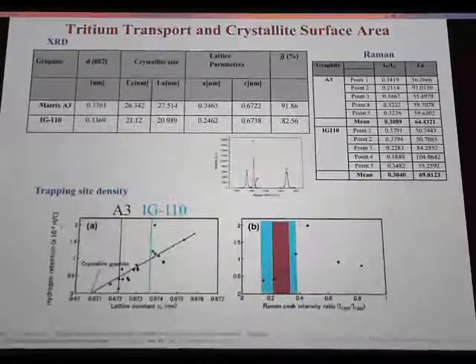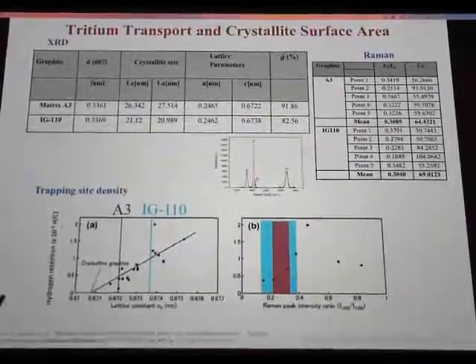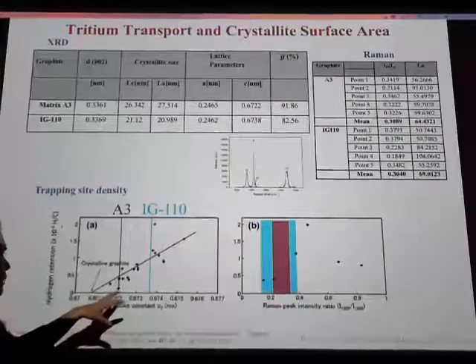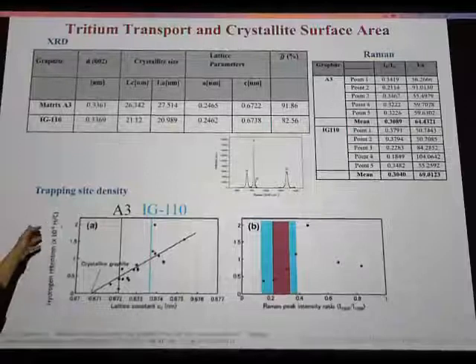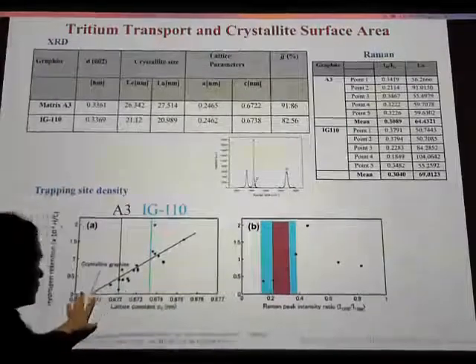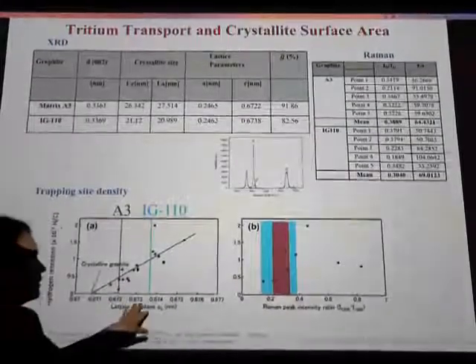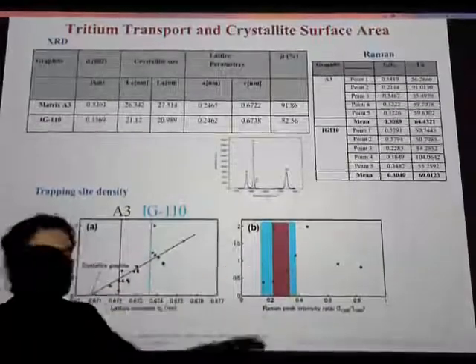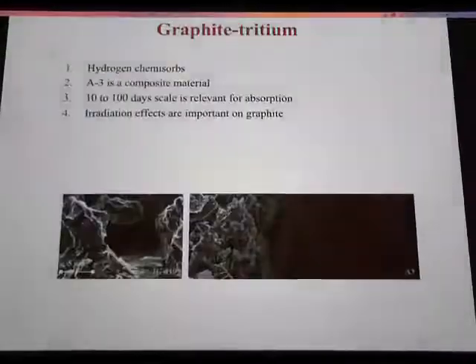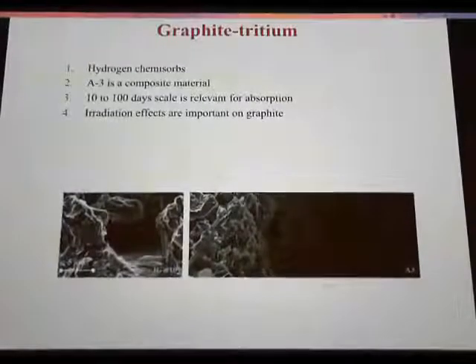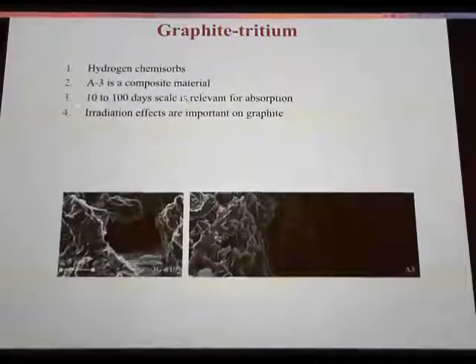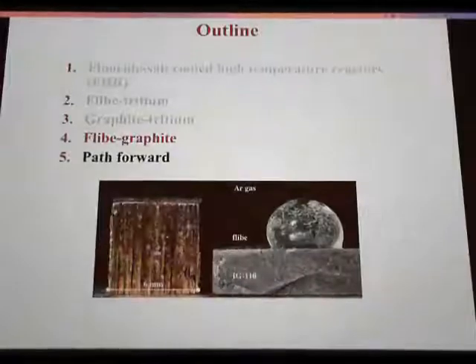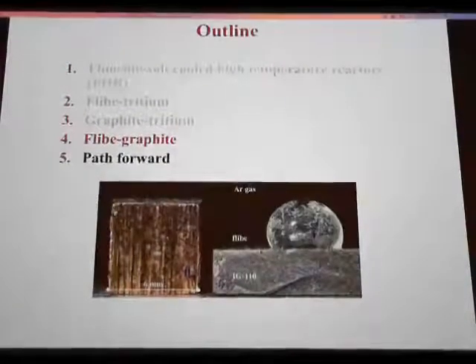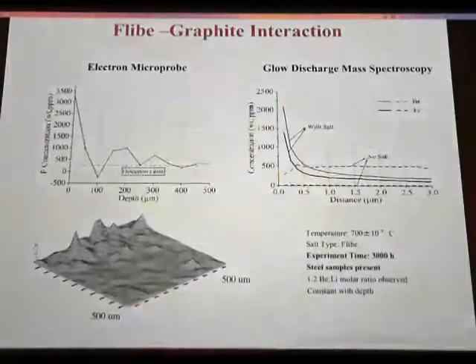Okay. And so then what microstructural characterization of these materials enables us to do is to predict things like trapping site density. And so here is some data for trapping site density versus the lattice constants of those graphite crystallites, and then this is where we fall for the materials that we've characterized. So a few takeaways: hydrogen chemisorbs, the timescale matters, and the irradiation effects are important. And then lastly, flibe and graphite will be a very quick conversation because I have 10 minutes left.